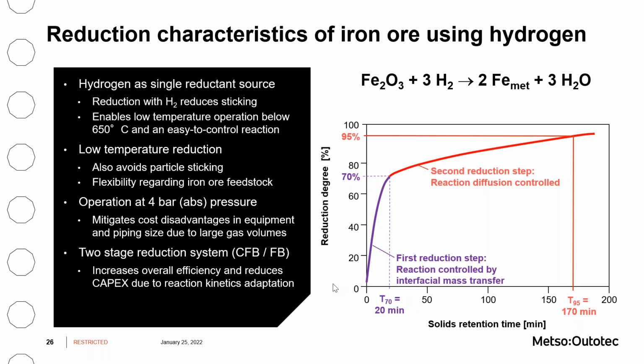Operating at elevated pressure of around 4 bars reduces the gas volume substantially. This helps to decrease piping and equipment size and therefore investment cost. It has no effect on the thermodynamic equilibrium of the reaction. Nevertheless, it helps to remove the product water from the recycled hydrogen gas via condensation. How these fundamentals translate into an industrial process is shown on the next slides.